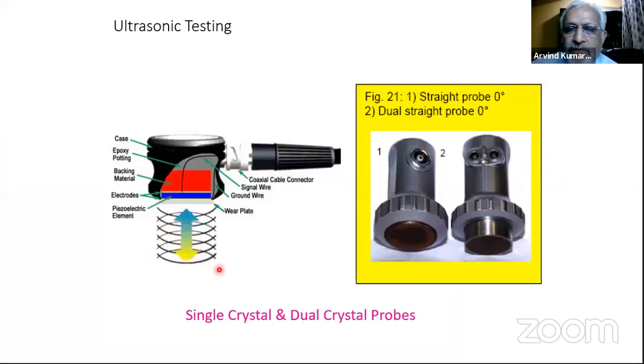Again, coming back to the normal beam probes, there could be a single crystal probe, where a single crystal is acting as a transmitter as well as a receiver, or there could be a dual crystal probe, which we call a TR probe, where one element is transmitting and the other element is receiving, both in the same probe. Here the single crystal is acting as transmitter as well as receiver, whereas here there are two crystals within the probe with a barrier which you're not able to see here. There are two connections you can see, one for the transmitter and one for the receiver. Here there is only one. So that is the difference between a TR probe and a normal conventional straight beam probe.